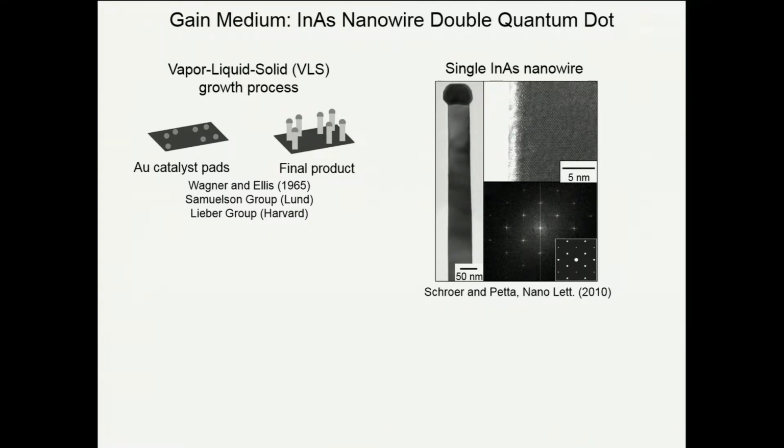We try to get the diameter so it's a couple of Fermi wavelengths. It's a quasi-1D channel that we can make our devices out of. And this is a transmission electron microscope image just to give you an idea of what a real nanowire looks like. These are grown downstairs. The diameter is about 50 nanometers. And you can see that they're highly ordered.